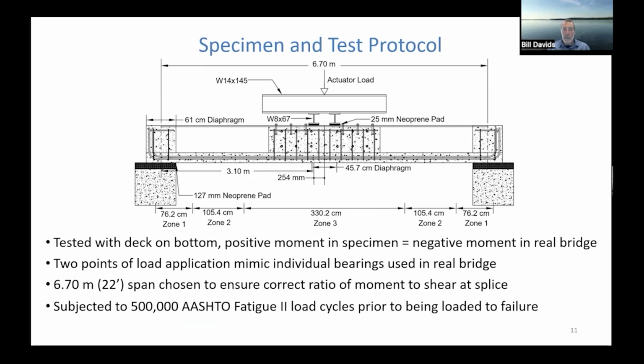And that span length of 22 feet was not arbitrary. That was chosen specifically so that we ensured the correct ratio of moment to shear at the splice. So when we produce MU, the factored moment, with our applied load we also produce V sub U at the splice, because we also have to carry shear with the splice. And we first subjected it to 500,000 AASHTO fatigue 2 load cycles prior to driving it to failure. We don't expect there to be any fatigue issues with this. We've assessed this shear friction connection in fatigue extensively in the past, and it's not a fatigue critical detail. We just wanted to settle the specimen and make sure there wasn't anything unexpected going on.